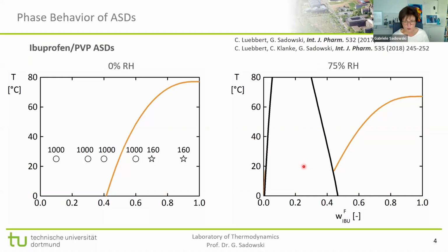And to check whether this is right or wrong, we again prepared samples having different drug loads and stored them at 40 degrees C and 75% RH. The reason is that the pharmacists have two different types of conditions where they have to store the samples and then to make sure that they stay the same. One is 25 degrees centigrade and 0% RH, and the other one is 40 degrees centigrade and 75% RH. So there are standard conditions for a pharmaceutical company where they have to store the samples over several months to show that the samples don't change during storage. Otherwise, you cannot bring them on the market. So that's why we have the samples here.